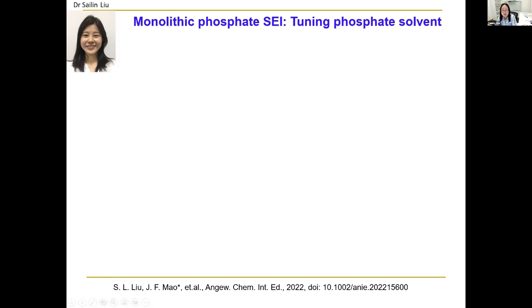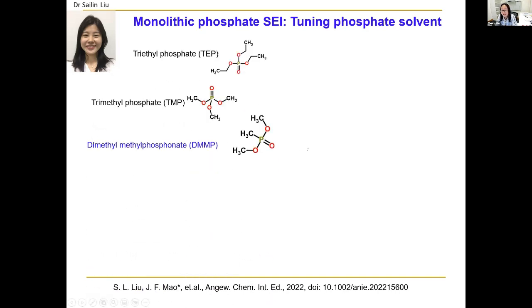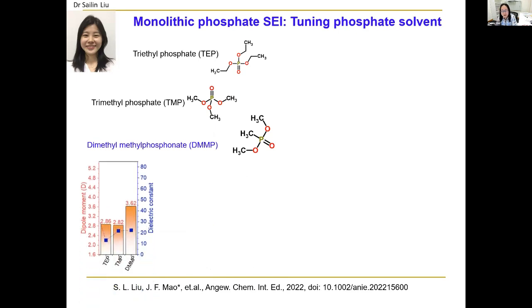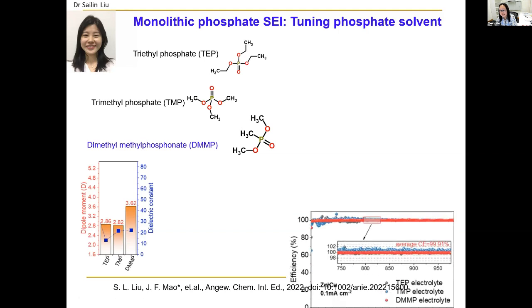So this is my postdoc fellow, Dr. Sailin Liu. She looked around at all other co-solvents that could be used, especially fire retardants, because we want to keep the non-flammability of the electrolyte. She found that DMMP is a kind of fire retardant that has a higher dipole moment. This higher dipole moment could make the electrolyte readily generate interface reactions and form a different kind of SEI.